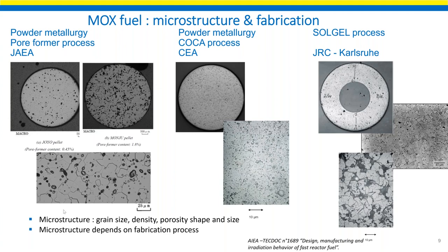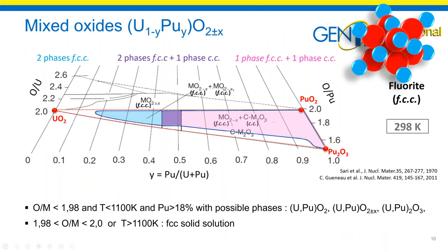The mixed oxide of uranium and plutonium has a face-centered cubic structure, FCC, with a fluorite type. The substitution of uranium by plutonium is possible until 100%. Y defines the plutonium content, and the deviation from the stoichiometry is noted X. When X is negative, it means that we have oxygen vacancies or actinide interstitials, and it's most of the time the case for MOX fuel.